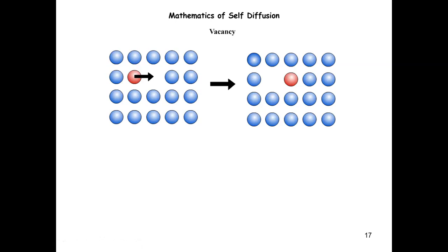And one important thing is that in order for these atoms to move around, right? In order for the substitutional diffusion to occur, a necessary condition is that you have to have some concentration of vacancy in the system, right? Because the mechanism for the diffusion of the substitutional atom is that this atom, at some time, is going to receive a sufficiently high activation energy from the thermal fluctuations, right? And make a hop from this original location to this vacancy site, right? After that, you can get this configuration.